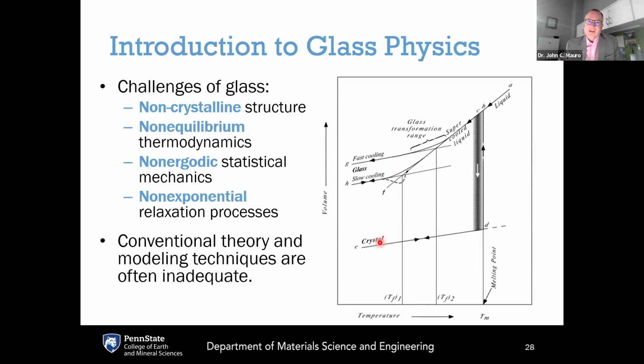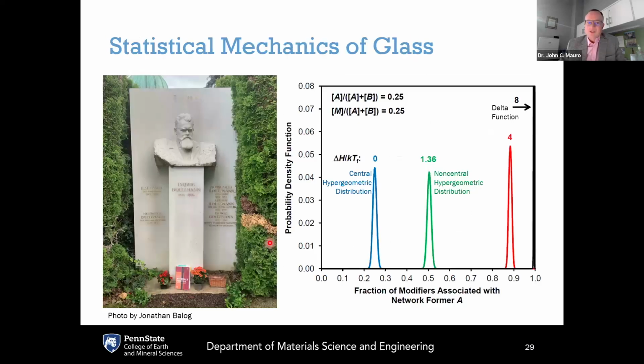So what we're observing in the glassy state is inherently a transient material. It is an out of equilibrium material. It's characterized by its non-crystalline disordered structure and its non-equilibrium thermodynamics. The relaxation towards the supercooled liquid follows a complex non-exponential pathway. It is what's called non-ergodic, which implies that the timescales of this relaxation process are very long. And even though glass is a very old material, it's at the forefront of material science because a lot of the conventional theories that we learned in school are simply not applicable to glasses. You can't just take standard equilibrium thermodynamics or standard crystal chemistry and apply that to glass, because glass is its own thing.